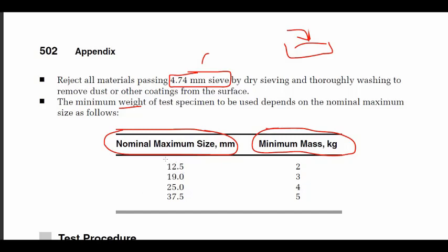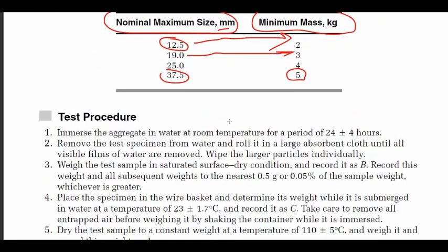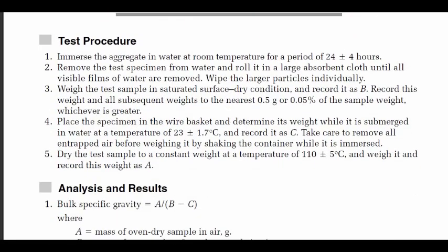So as you can see here, if you have the maximum size of the aggregate to be 12.5 millimeter, then you are going to have the sample to be like 2 kg. And if it's 19 millimeter, the maximum size, then you're going to have 3. And if it's 25, then you're going to have 4. If it's 37.5, which is bulky, then you're going to have 5 kg of the sample. So now we covered the sample itself. Let's go now to the test procedure itself.